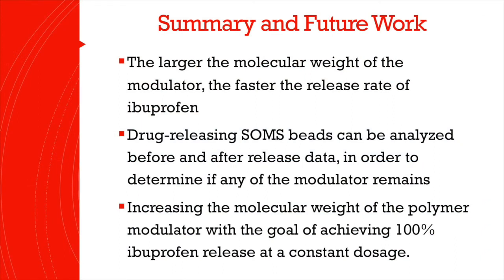The main conclusion of this research that we saw was that the larger the molecular weight of the modulator, the faster the release rate of ibuprofen from these SOMS beads, and the more ibuprofen was released from these SOMS beads. Some future work that can be done would be to analyze the drug-releasing SOMS beads before and after the release data of ibuprofen is collected in order to determine if any of the modulator also remains entrapped in the SOMS beads. Something else that we can do is to increase the molecular weight of the polymer modulator with the goal of achieving 100% ibuprofen release at a constant dosage, which, as we saw 2 slides before, a constant dosage was achieved for about 24 hours, but after that it started to dip off.